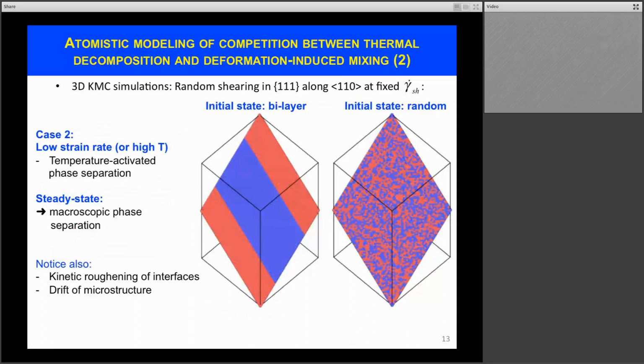Let's, in the second case, now consider a situation where the strain rate is low compared to thermal diffusion. And what we see is that that same bilayer now is evolving much more gently. There is a little bit of roughening of the interface. Some steps are formed, but you can see that essentially the two-phase coexistence is preserved during shearing or during deformation.